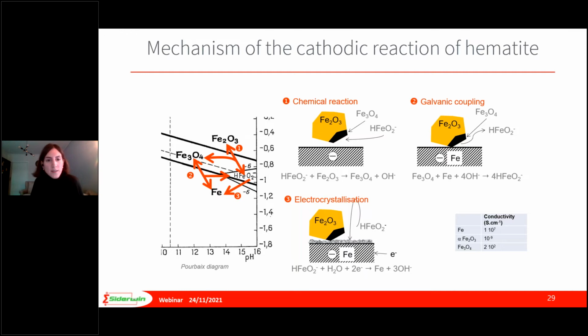To be more precise, first, the divalent cations that are dissolved in the solution react with the hematite particles, producing magnetite. At the same time, the deposition of dissolved iron ions takes place at a low rate. After that, the iron oxide particles are adsorbed to the cathode, and the magnetite reacts with the metallic iron and the hydroxide ions, resulting in an increase of the divalent iron ions in the electrolyte. So, the reduction of divalent ions from the iron oxide dissolution plus the magnetite reaction with iron that was previously deposited on the cathode results in the production of metallic iron. It is impossible to have this high rate of production without the contact of the particles with the cathode.